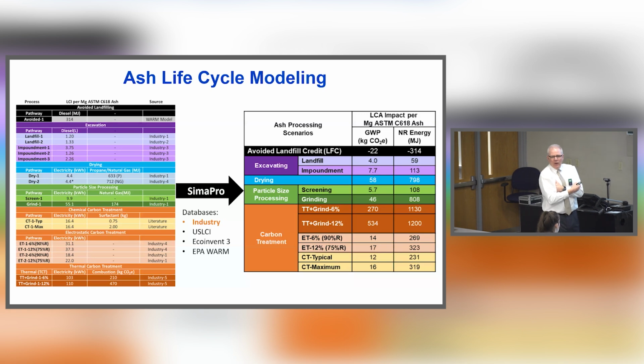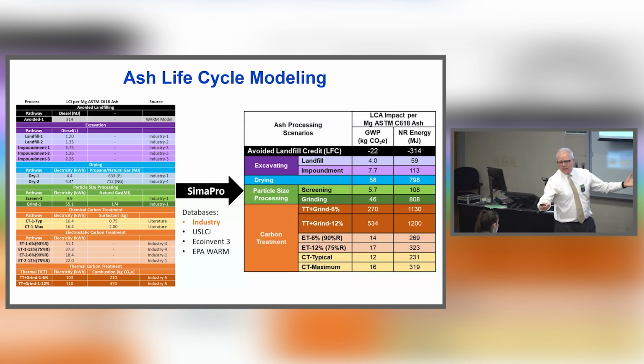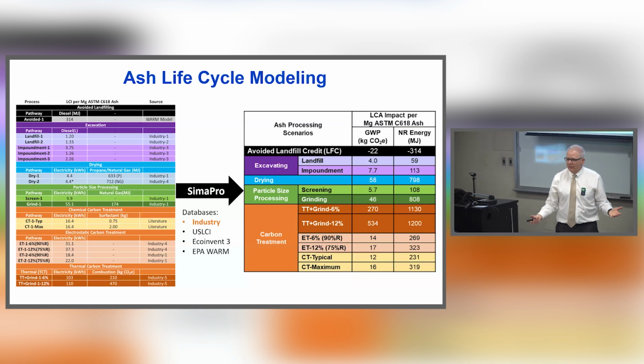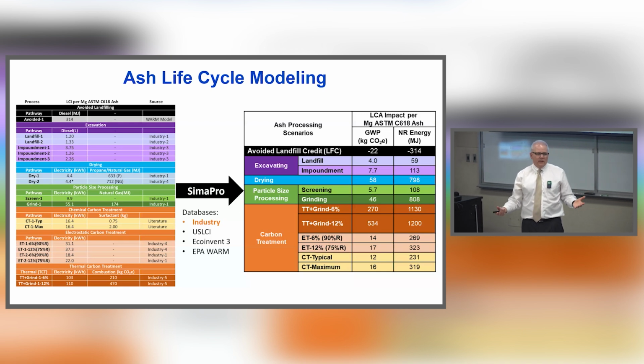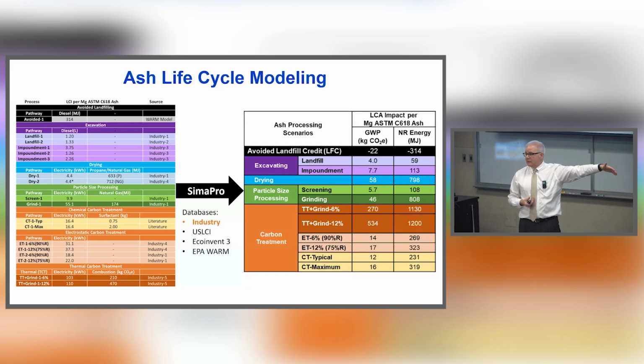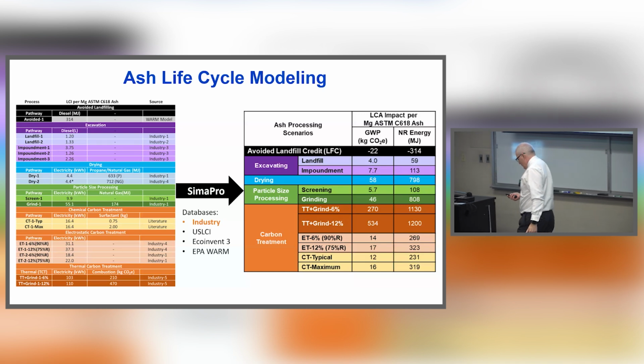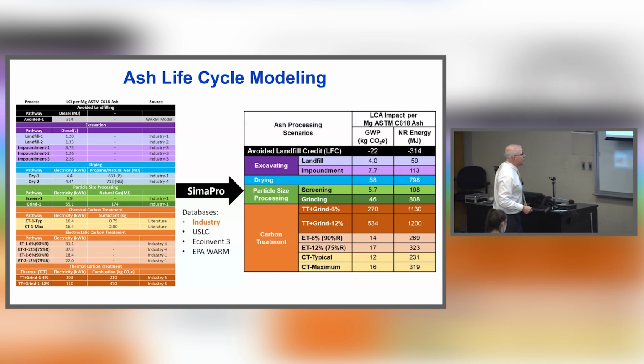It's heavier, full of water. So I'm in there excavating it, and half of my mass I'm pulling out, maybe not half, maybe a third, is water, right? That I don't even want, but I've got to pull it out. That's not true in my landfill. I have very little moisture in that as well. In fact, at the dry ash landfills that are being harvested, they actually use it without even drying in most cases, which is pretty remarkable. But yeah, so it just takes more work, right?